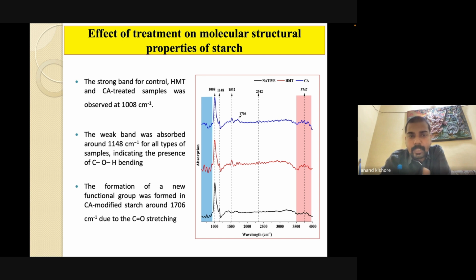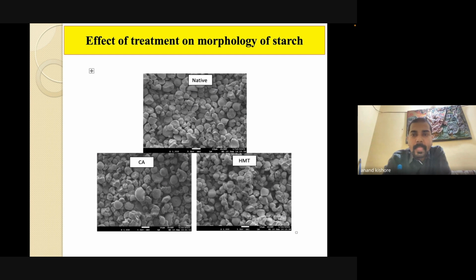The weak band was absorbed around 1148 for all types of samples, and the major peak we found at 1008 centimeter inverse. If we did the same analysis for the effect of treatment on the morphology of the starch, we found that there is some cluster formation after modification, in the CA and HMT starch. So the cluster formation may be because, after the modification technique, there is a formation of bonds between the molecules. So that may be the reason there is a formation of clusters, and the surface is not a packed structure if you compare it with the native starch.